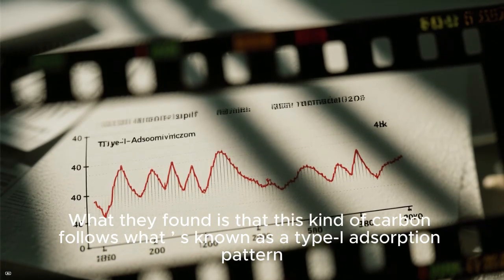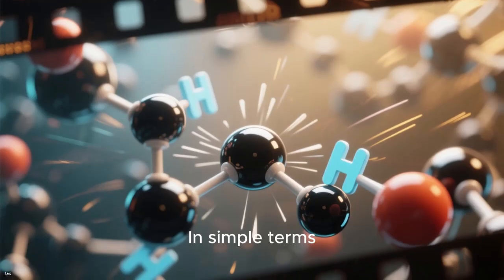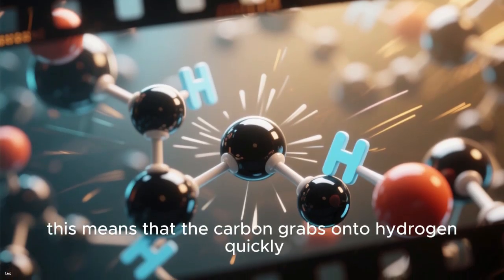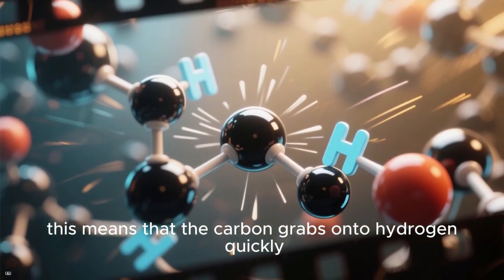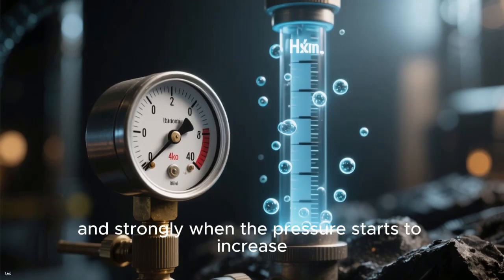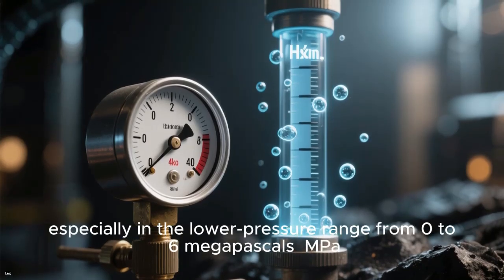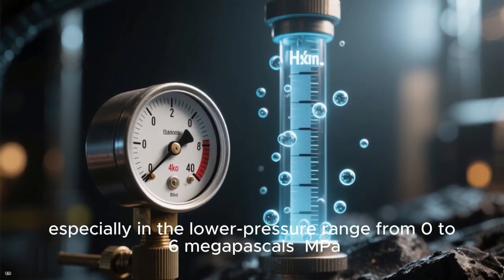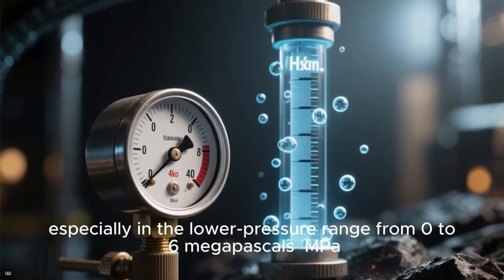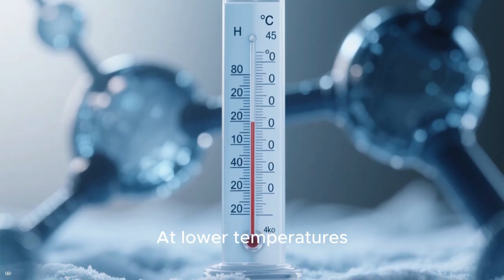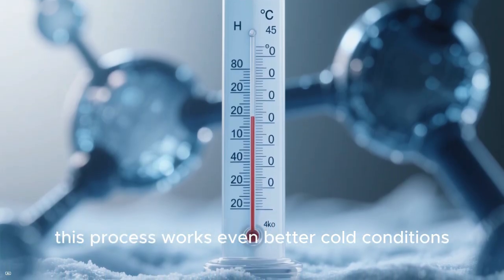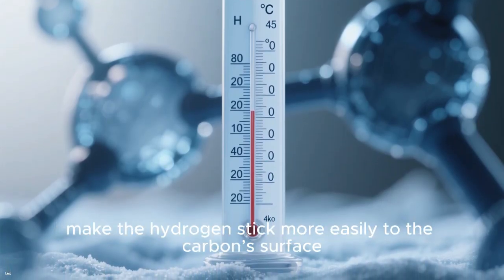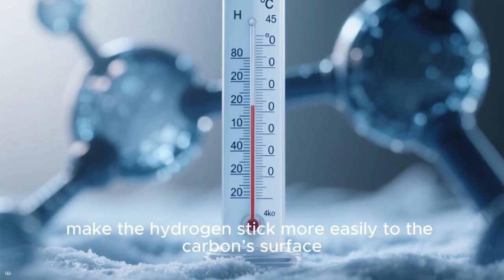What they found is that this kind of carbon follows what is known as a type I adsorption pattern. In simple terms, this means that the carbon grabs onto hydrogen quickly and strongly when the pressure starts to increase, especially in the lower pressure range from 0 to 6 megapascals (MPa). At lower temperatures, this process works even better. Cold conditions make the hydrogen stick more easily to the carbon's surface.